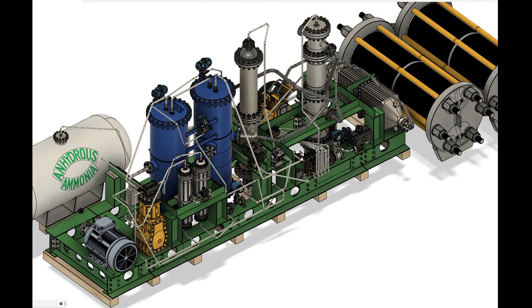In the liquid phase it is 285.83 kilojoules per mole. Since commercial electrolyzers almost exclusively split water in the liquid phase, the number of 285.83 kilojoules per mole is used. This translates to 4.4 kilowatt-hours per kilogram of water split. Since H2O is exactly 11.19% by mass hydrogen, the minimum energy consumption to split water is 39.39 kilowatt-hours per kilogram.